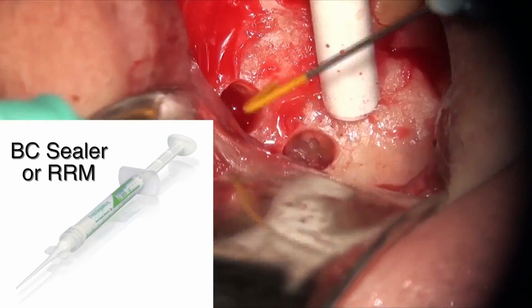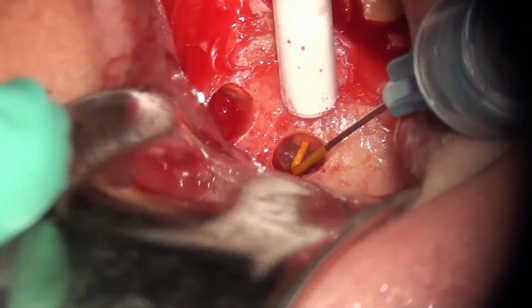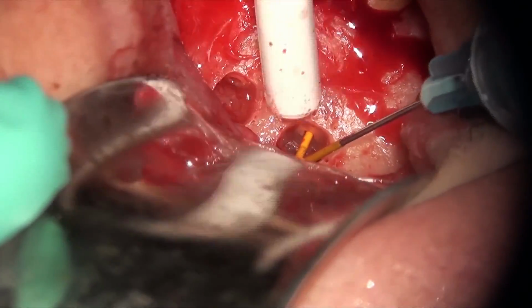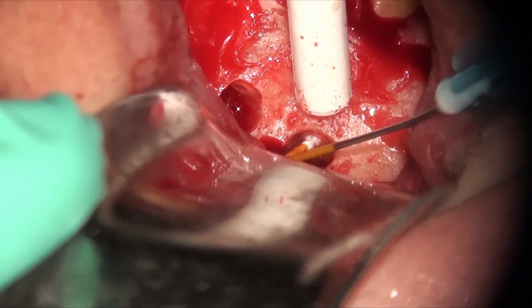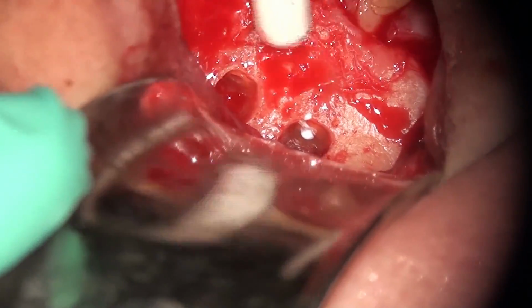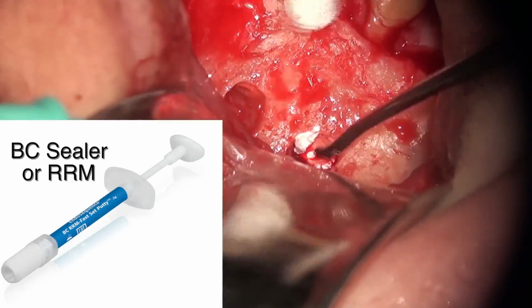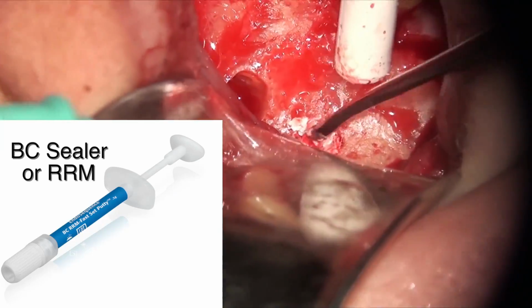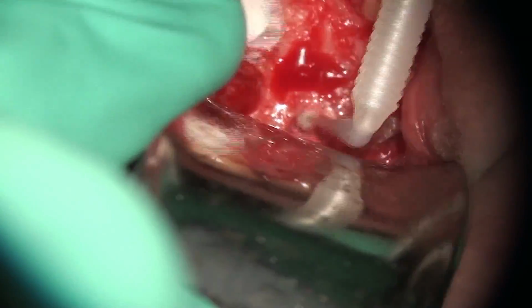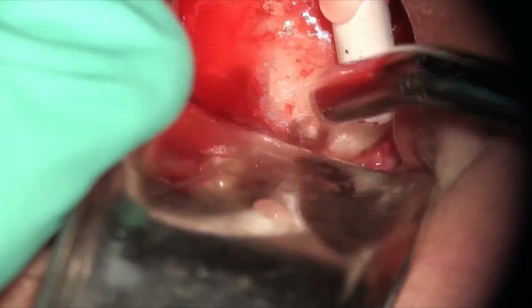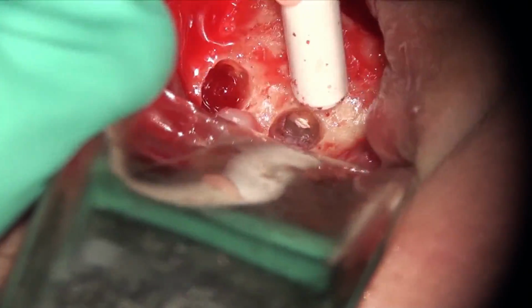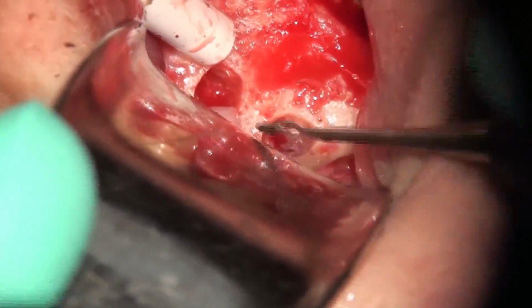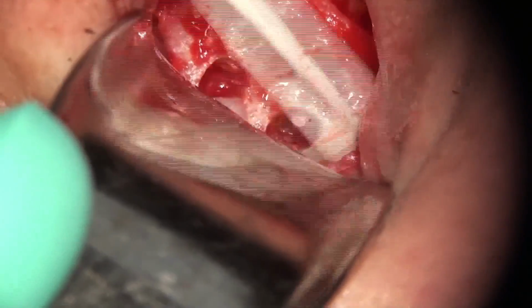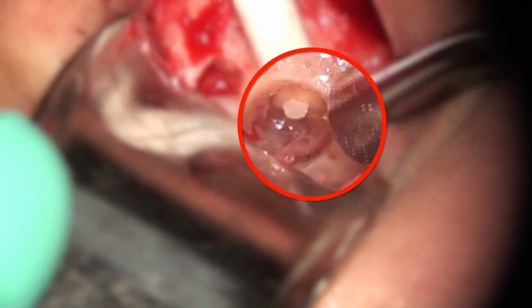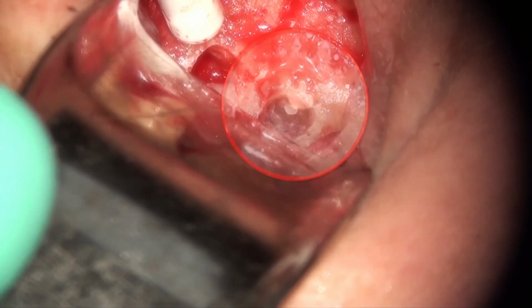is all gone, and then you basically place the injectable material, making sure that the tip of your nozzle goes all the way down. As you can see in this technique, because it takes so little time to fill these canals, you require minimum use of chemicals for hemostasis. After you've injected your material, the syringeable material, in the dry conditions, if you get a little bit of blood in there while you're putting the putty in there, it is not as important. But during the placement of the syringeable material, you have to make sure that you have a very dry field, which will really take only about 10 seconds.